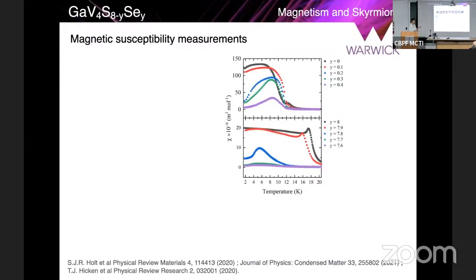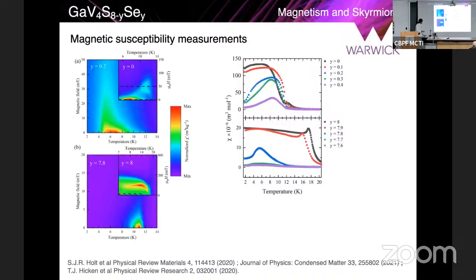So you can see what happens as a function of... okay. So if you look at the magnetic properties here, this is magnetic susceptibility as a function of temperature. Once again, you see that for compositions very close to the end materials, a different behavior to those quite far away from the end materials.